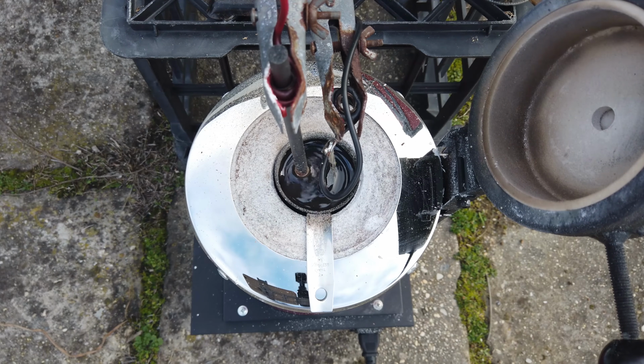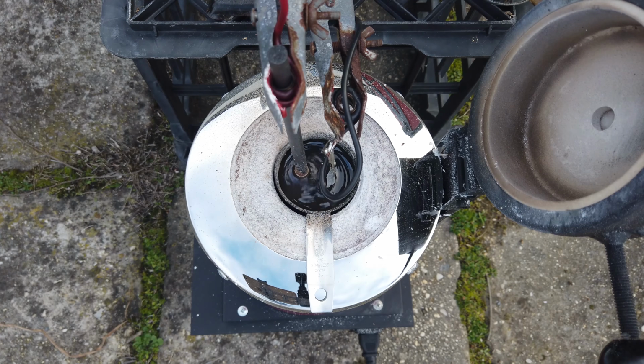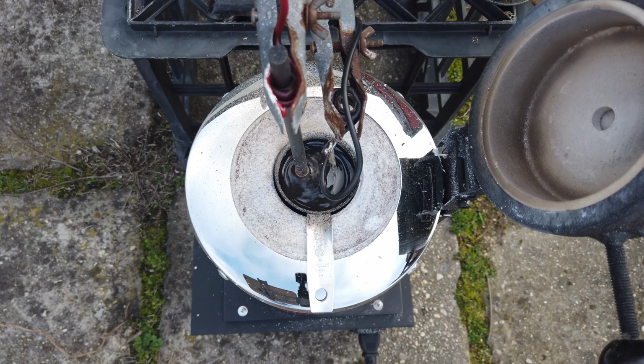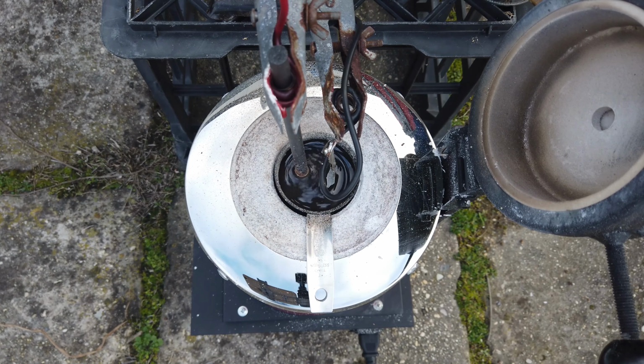Alright, I think I'm going to call it for this one. We've had it running for about 10 minutes. We're seeing a lot of chlorine on the anode, but on the cathode we're not generating much in the way of lithium. I do see a couple of tiny specks every now and again of very shiny, what I assume to be molten lithium from our melt, but they disappear very quickly, and I think we just don't have the right setup to generate lithium like this. I think we might require an inert atmosphere or something like that, maybe argon or something. So I'm going to turn this off,